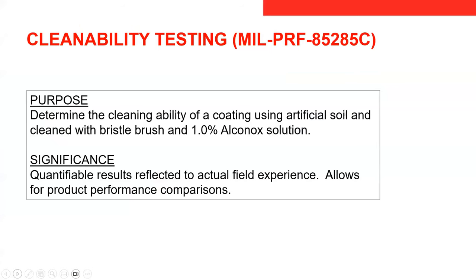So a test that we've determined to be very useful and actually correlate very nicely to what we experience in the field with our coatings is a cleanability test. It's MIL-PRF-85285C, very specific. And it's used a lot in the aerospace industry, where they use an artificial soil, and then that's cleaned with a bristle brush and a solution. And you're able to get quantifiable results on how much of that artificial soil was removed through the cleaning process. And again, we feel it correlates very nicely with what we've experienced, our customers have experienced in the field with different top coat technologies.